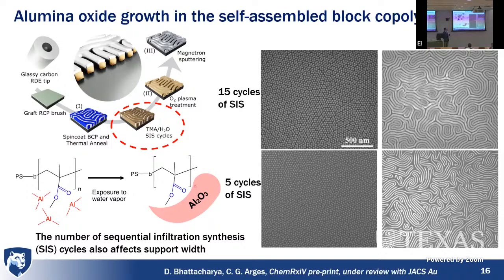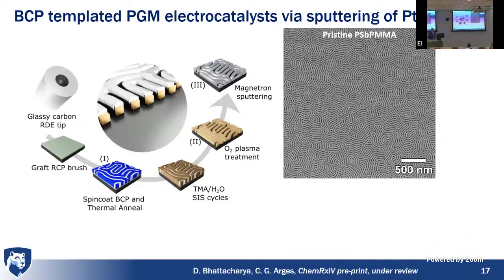block copolymer. So the SEM images that you're looking at right here, this is after we've etched away the polystyrene with oxygen plasma. And these are perpendicular cylinders, right? And these are lamellae structures, right? So again, we're using that block copolymer template to control the mesoscale morphology. And then we can use another handle to control the support width through the SIS process. So this is our block copolymer template.